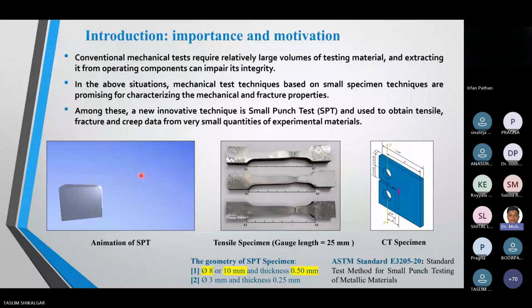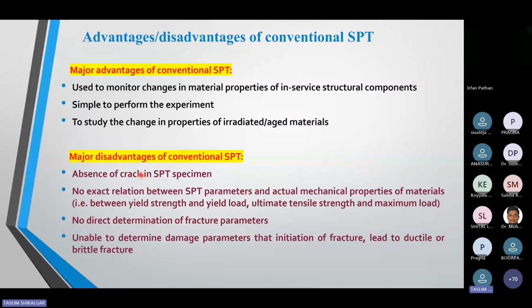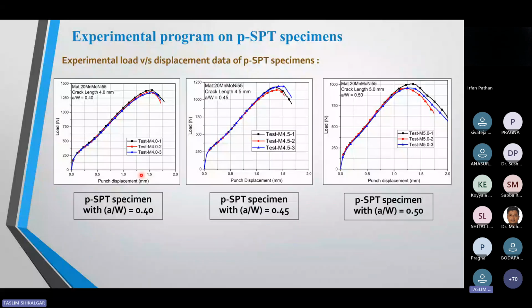Normally, what material are you testing? 316LN or P91? No, I tested only nuclear pressure vessel materials. There are two to three materials basically being used. One is T91, the second one is 20MnMoNi55, and another one available is 304L. In old pressure vessels they used 304L, but now they are using T91 and 20MnMoNi55. These materials have been used for the last 20 years. Okay, that research is on austenitic, low carbon austenitic steel, 316L, 304L, that category of steel. And P91 is a modified 9 chromium 1 molybdenum steel. Yes, that category.